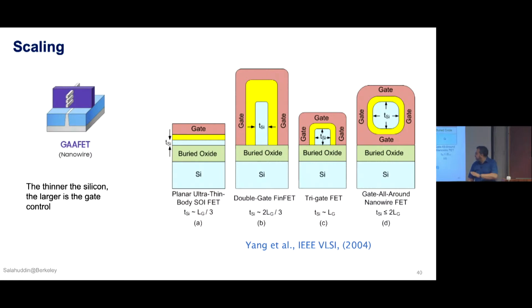I will say that this is a little bit too aggressive, but we say that at 3 nanometers thickness, you should be able to get down to around 6-7 nanometer of LG.